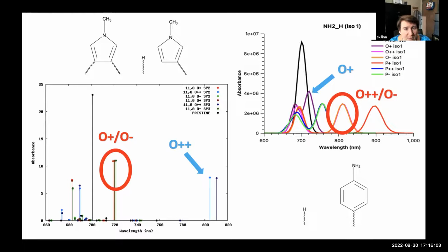So technically from spectral features, the difference between sp2 and sp3 peaks in this case, for the most redshifted, is more noticeable, but still small, right? Because check, like about 10 nanometers difference here. If you convert it to electron volts, it would probably be a very, very small difference. And in case of the more blue shifted transitions, which are degenerate for both cases, the difference is even smaller, right? Almost impossible to differentiate.